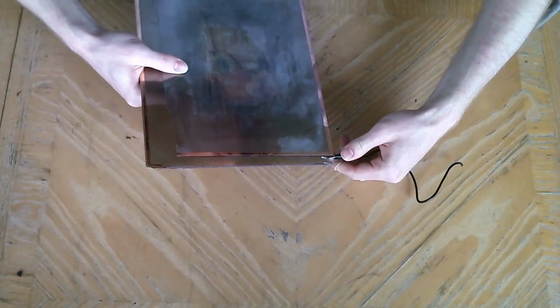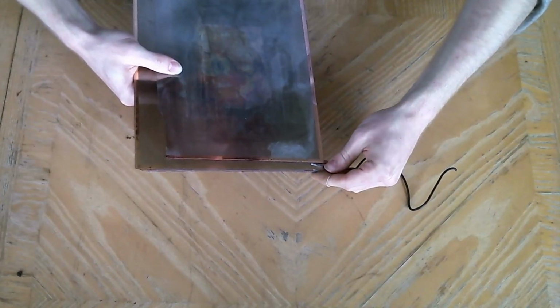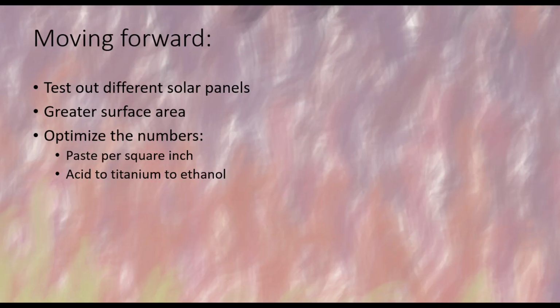I was really happy with how this product turned out, and although for the particular one I recorded for this video I wasn't able to check how much voltage it pulled, on my most powerful solar panel I was able to pull about 0.4 volts per square foot, which is about a third of the power of one of the portable solar panels you can buy off a site like Amazon. I was really satisfied with that result, although that was only in a very small rectangular area, and then I did the math to figure out the volts per square foot. But actually creating and pulling that voltage from a square foot would have been very difficult given these items.